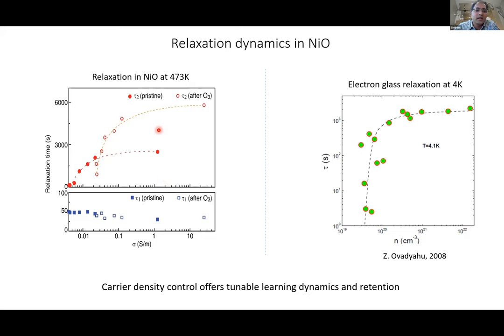And why is this interesting? This is interesting because this is very similar to electron glass behavior seen in disordered insulators, in this case at about 4 Kelvin. So this is relaxation behavior as a function of conductivity. And this is a very similar experiment done at almost 400, 500 Kelvin higher temperature on nickel oxide. But you can see very similar relaxation dynamics. What this tells you is that the relaxation timescales can be controlled by controlling the ground state conductivity, which is very important because then this allows you to do more experiments on learning and forgetting.